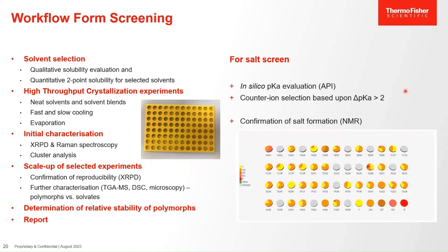And then we select suitable counter ions based on a general rule that says salts are formed if the difference in pKa between the two components is greater than 2. Sometimes you will see a number greater than 3 here. There is a bit of a gray area between difference of 0 and difference of 3, because there you might be forming something between a salt and a co-crystal. So how do we actually carry out these activities?